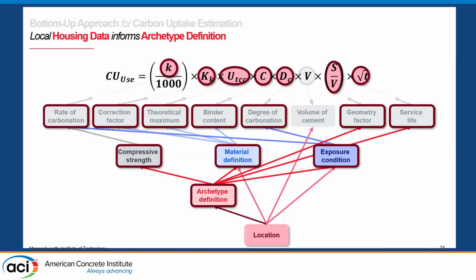Lastly, local data includes housing data or other information about the building stock, which helps us define the archetypes, which in turn helps us identify the breakdown of compressive strengths, because you have a variety of different building elements and building heights that could lead to higher or lower compressive strength use. The material definition, for instance, some archetypes have infill walls, which are concrete masonry units. Others have concrete structural frames, and it affects the breakdown of mortar applications versus concrete, cast in situ concrete applications. And the archetypes also inform exposure conditions, because it helps us break down the amount of surface that's outside, outdoors, versus indoors, versus in-ground, such as the foundation.